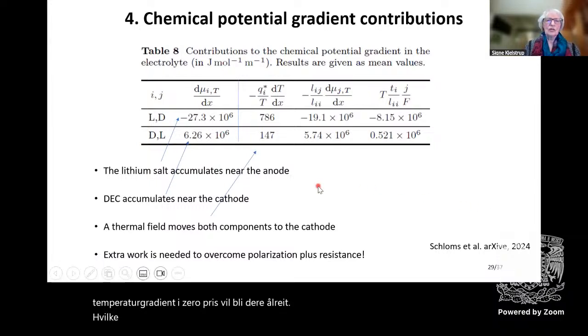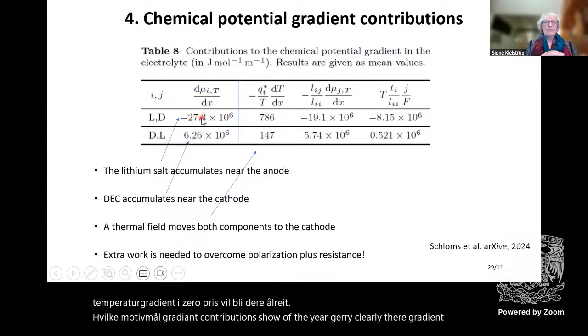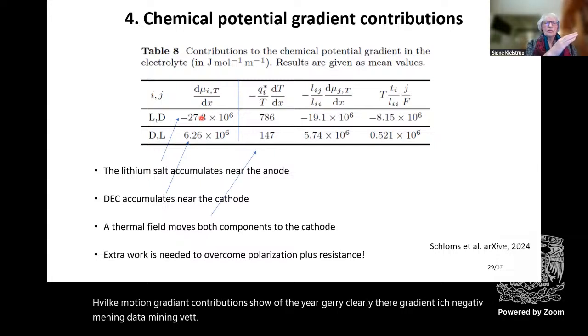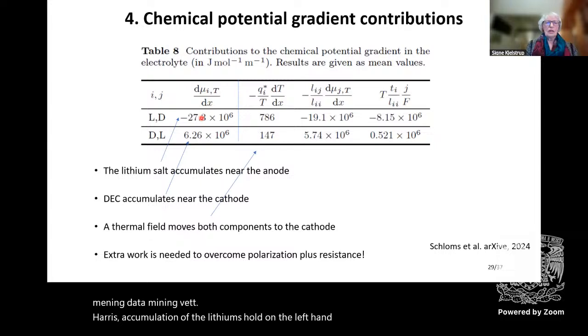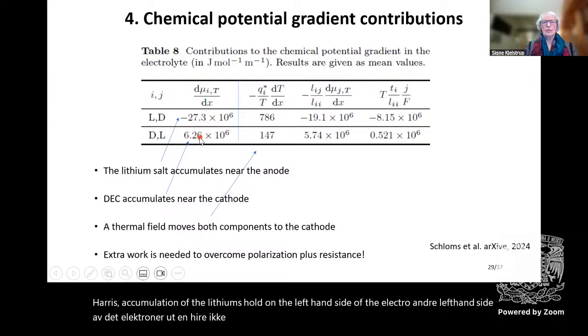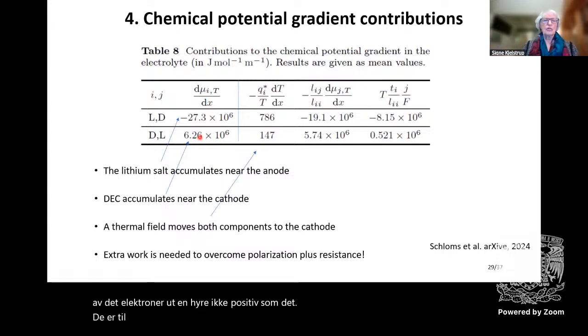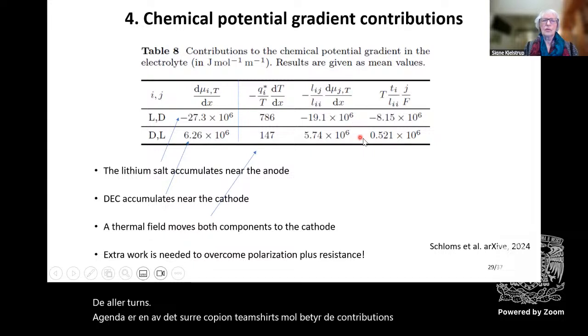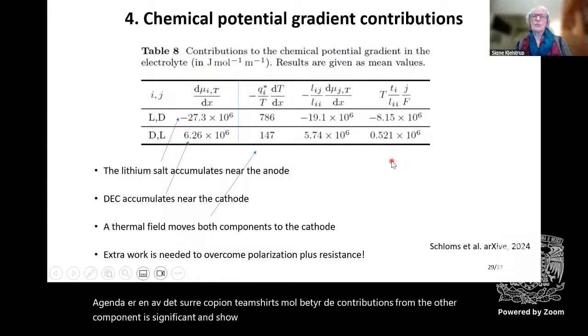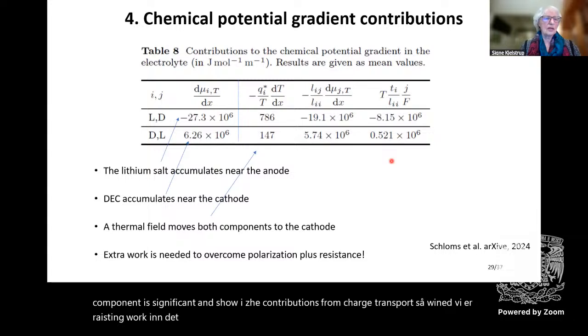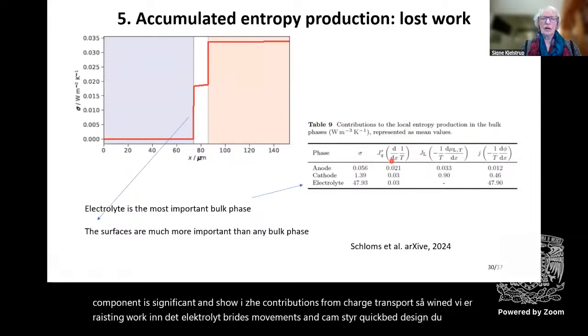The chemical potential gradient contributions show also here very clearly that the gradient is negative, meaning that there is accumulation of the lithium salt on the left-hand side of the electrolyte, and here it's positive, so the diethyl carbonate is accumulating on the other side. The other terms, again, in the anode, the Fourier coefficient terms are small, but the contribution from the other component is significant, and so is the contribution from charge transport. So we are wasting work in the electrolyte by these movements, and the chemistry could be designed to take care of that, I would think.